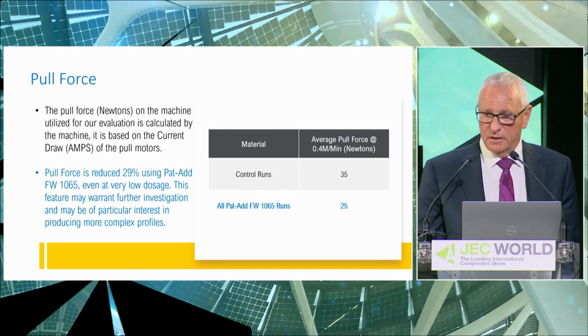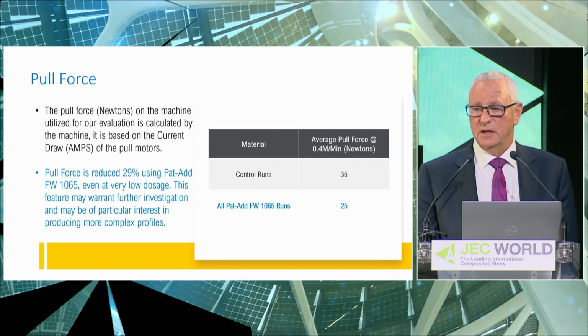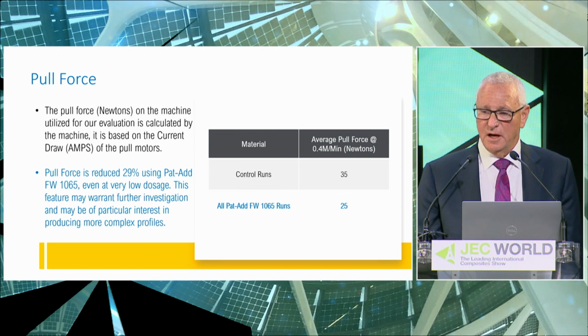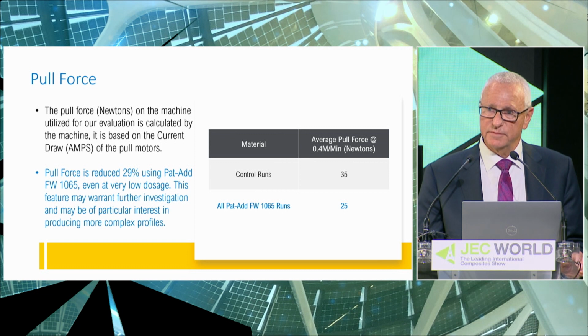Something we noted right out of the gate, fairly interesting, was the pull force as measured on the machine. In this particular case, the machine just measured and converted it to pull force based on the amperage draw of the pull motors. And it's, again, a significant reduction in pull force. It went from 35 newtons down to 25 newtons. Everything was kept the same.